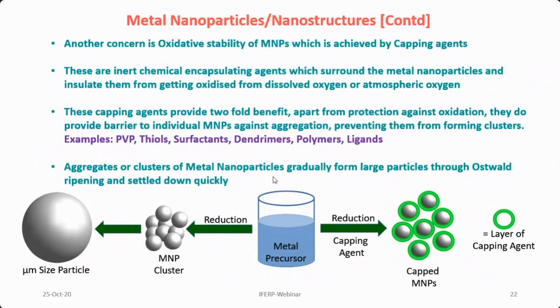At the same time, it gives a double benefit. Another benefit is that it provides a protective layer against aggregation, because these nanoparticles have very strong aggregating forces, so they tend to aggregate very quickly. They come close together, aggregate, and then with Ostwald ripening, they slowly form micron-size particles. Your experiment will slowly fail, because you will end up getting micron-size particles.